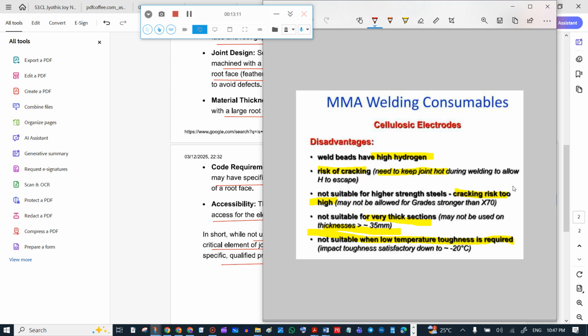Again, we have this cellulose. We are going to discuss the disadvantages. It has high hydrogen, so there is a risk of hydrogen induced cracking. We need to keep the joint hot during the welding to allow hydrogen to escape. There should not be rapid cooling, otherwise cracks will appear. It is not suitable for high strength steels. Cracking risk is too high; it may not be allowed for grades stronger than X70.